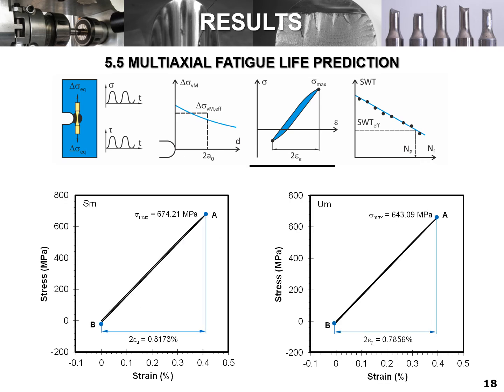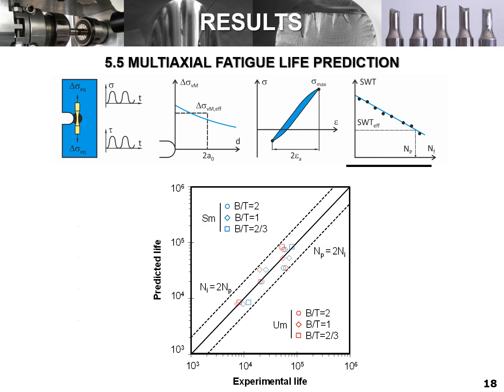The effective value of the von Mises stress range was then used to generate the cyclic stress-strain curves by applying the equivalent strain energy density concept, which were used to compute a representative value of the SWT damage parameter. Once again, the generated hysteresis loops are quite similar, regardless of the mesh type selected in the analysis. We can estimate the multiaxial fatigue lives.